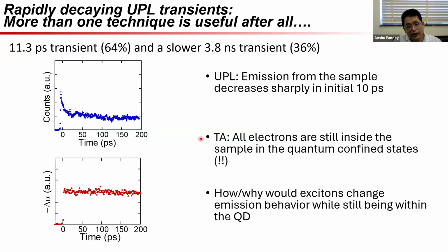If we look at transient absorption, we find that there is a bigger contradiction brewing. Because if we look at luminescence upconversion, it's trying to tell us, well, the emission from the sample decreases very sharply in the initial 10 picoseconds and then seems to be sort of stabilizing. Okay, the transient absorption in fact says, okay, look, I'm nice and clean, and all electrons in this same time frame are sitting in exactly the same state. The states are not changing.